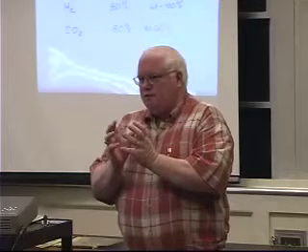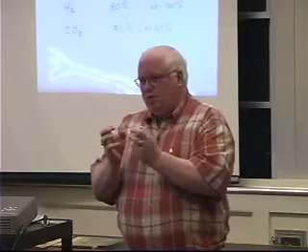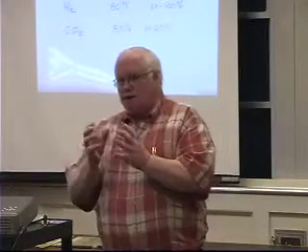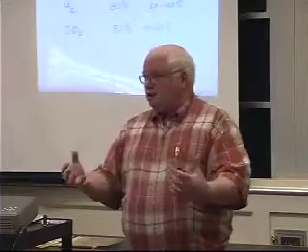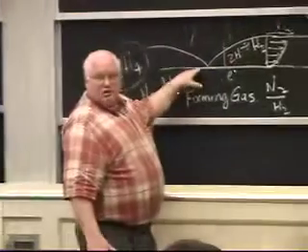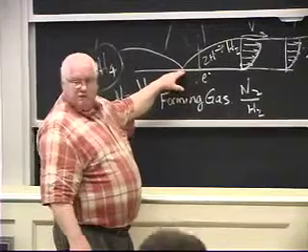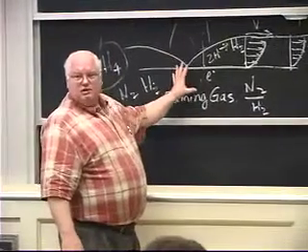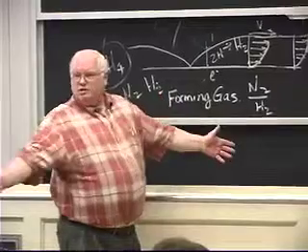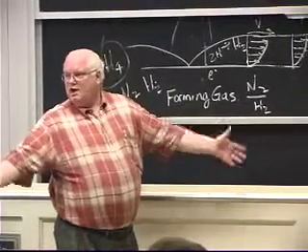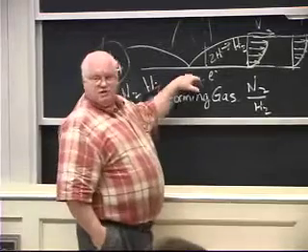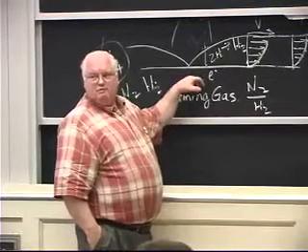But in terms of melting efficiency, heat to melt the fused area, they're only about 20% efficient in an argon arc, let's say. 50% of the heat got into the workpiece, but only about 20% of the total, which is 40% of the 50, goes into melting the weld pool, and the rest of it goes into creating the heat affected zone, heating up the solids surrounding the weld pool. So 50% gets in, but it's less than 50% efficient again at melting metal.